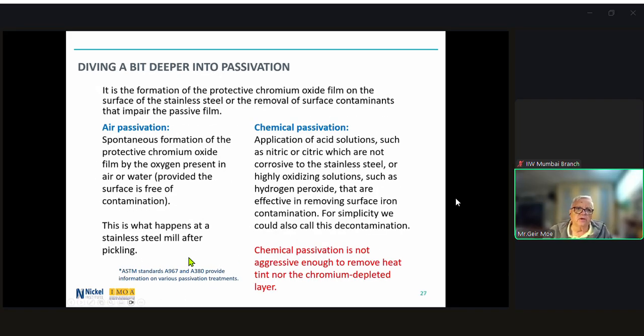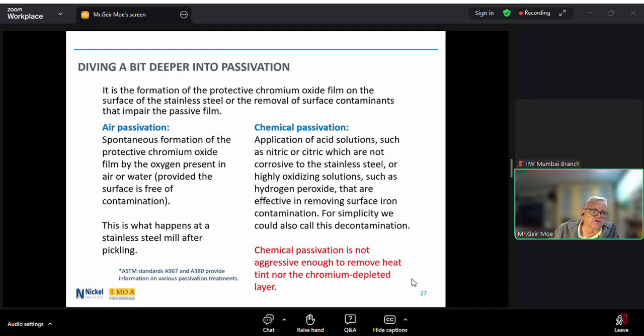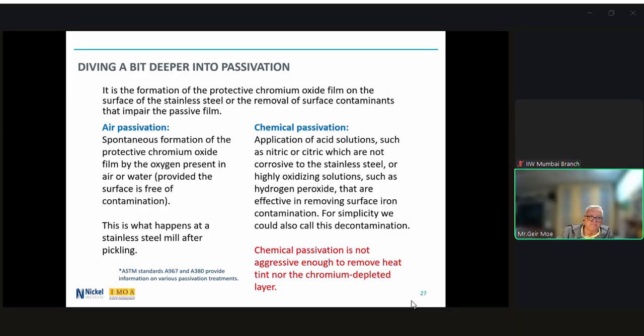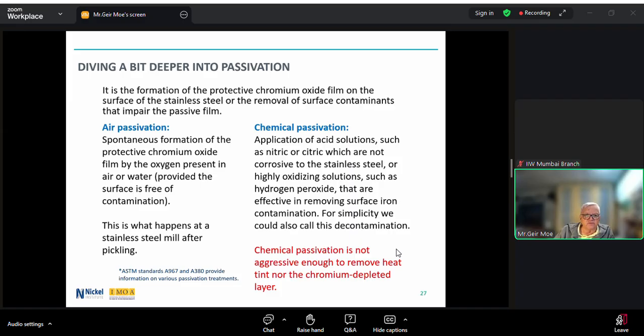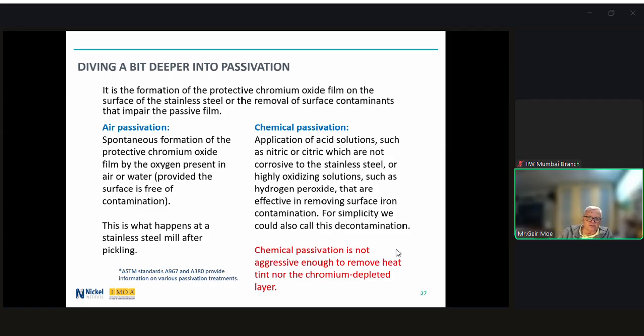So diving a bit deeper into passivation, we know passivation is the formation of a protective oxide film on the surface of stainless steel, or removal of surface contaminants that impair the passive film. So we can divide passivation into two types. Air passivation, that is the spontaneous formation of the protective chromium oxide film by oxygen present in air or water, provided the surface is free of contamination. And this is what happens at a stainless steel mill after pickling.